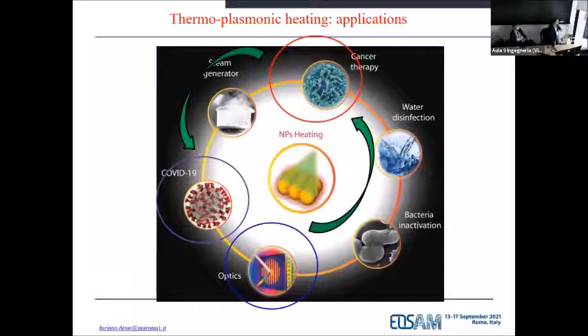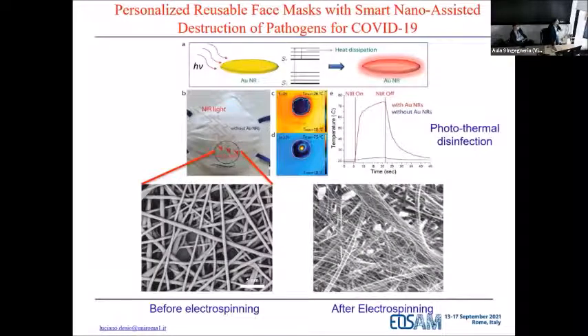So then we decided to make an amazing face mask, where by utilizing gold nanoparticles with exotic shapes like nanorods and even bipyramids, we are now able to deposit those particles on the face mask. Once you trigger near-infrared light, you can raise the temperature up to 75 degrees C, and this is more than enough to kill, to suppress viruses. That's why this is a starting point.